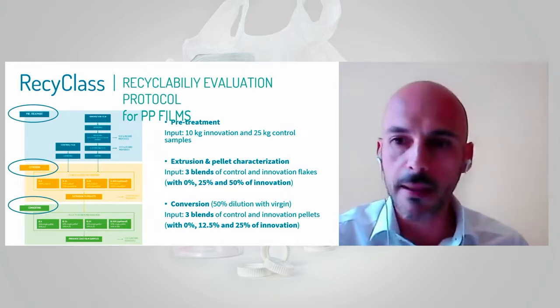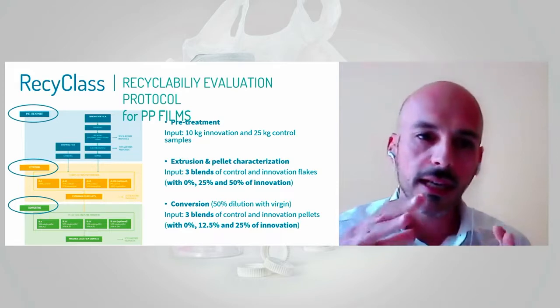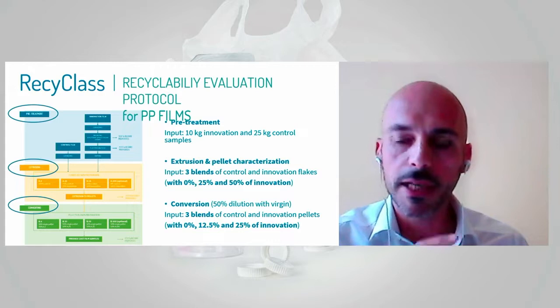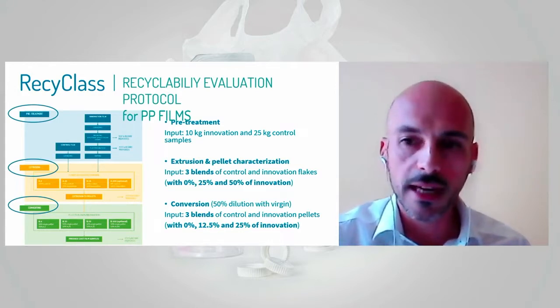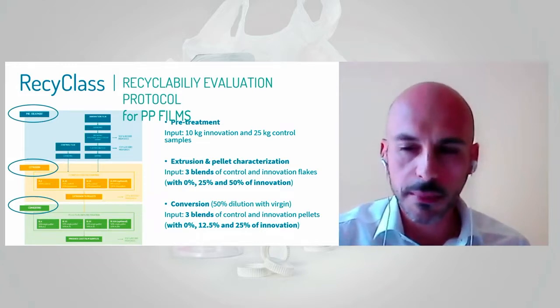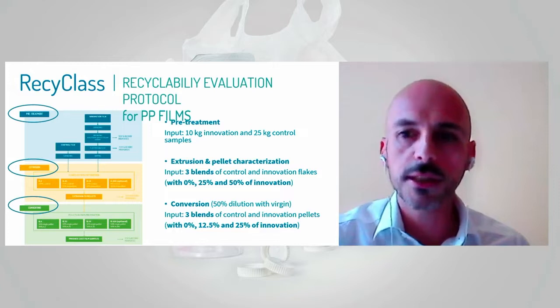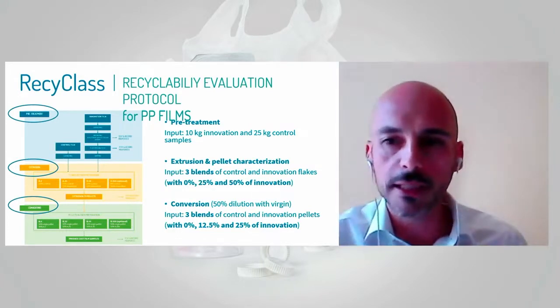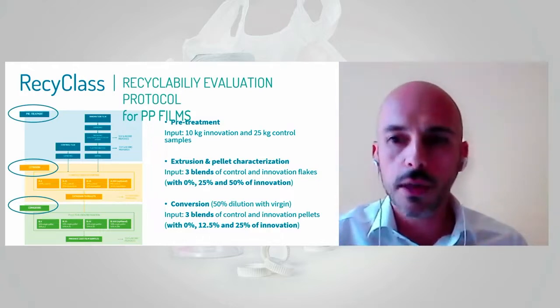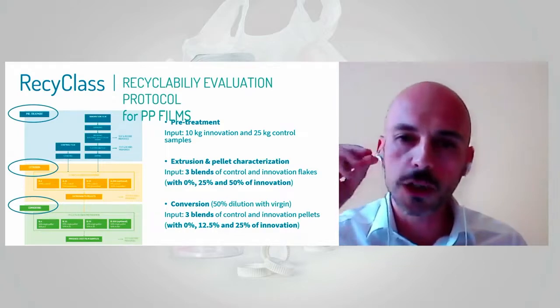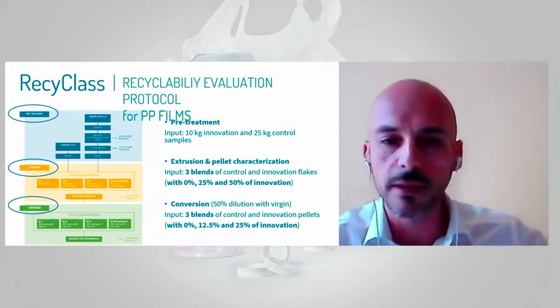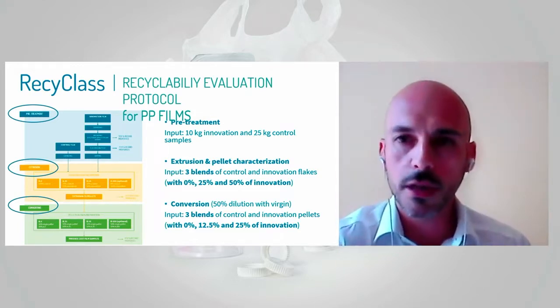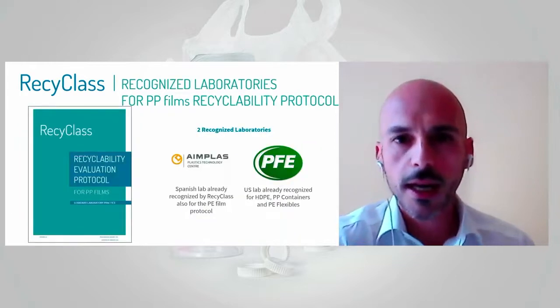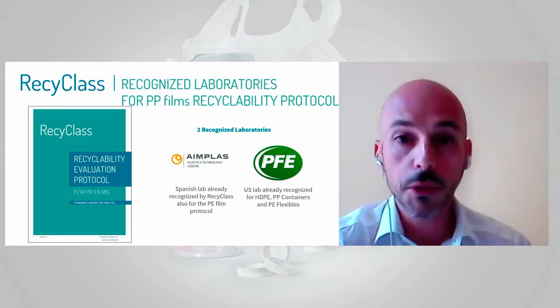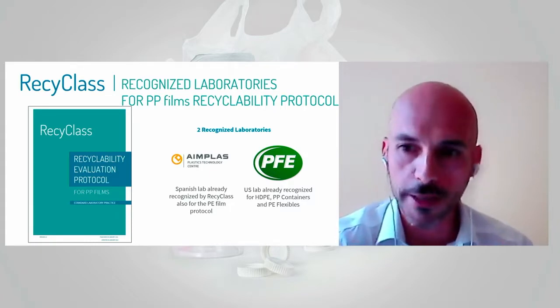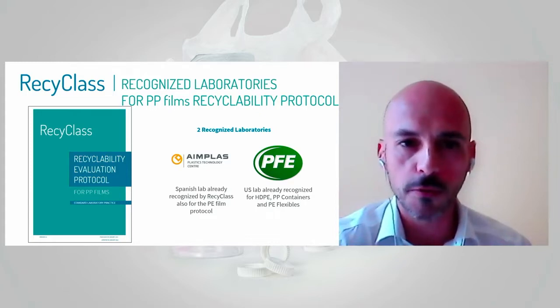But the third step, the most important one, targeting circularity: the recyclates produced by the previous step are diluted by half with virgin and are processed for cast film production. Once again, for 30 minutes minimum time, with different concentrations of innovation. And then the films are collected and compared with each other for the tensile properties and visual inspection, in order to understand if the innovation film technology can determine a negative influence in the tensile properties or in the visual evaluation of the film. We have 2 recognized laboratories, one in Europe and one in the US, and we are also looking to have an owner fully recognized for managing our protocol for polypropylene films.